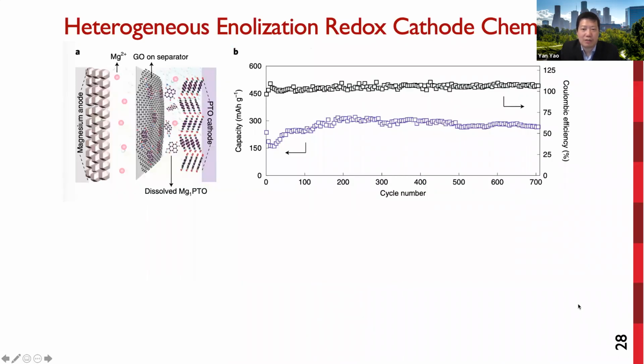Like other liquid-solid reaction-based batteries, soluble reaction intermediates bring two major concerns. First is a cathode mass loss caused by continuous dissolution. And second is that dissolved species will diffuse to the anode side and cause passivation of the metal anode. So both of these issues were controlled effectively in our system.